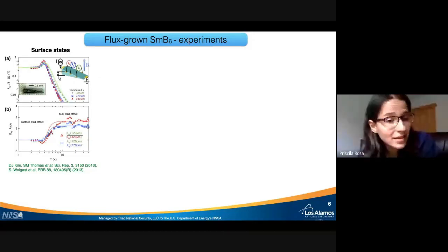So it's independent of the thickness of the material because the Hall resistivity deals with the thickness of the material in bulk systems, but in the case of a surface state, that doesn't hold anymore. So you can see that the ratio between the Hall resistances here below 5 or 4 Kelvin goes to 1. So I think the community right now, it's been 7 years already, right? So the community agrees, and there's a consensus that there are surface states.